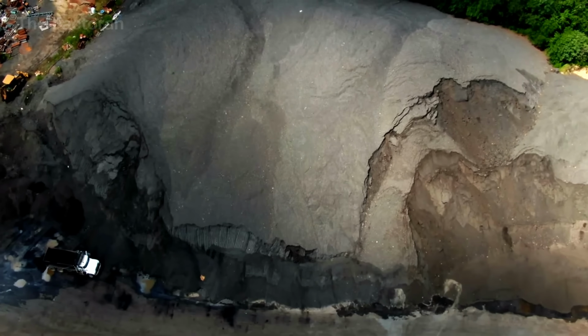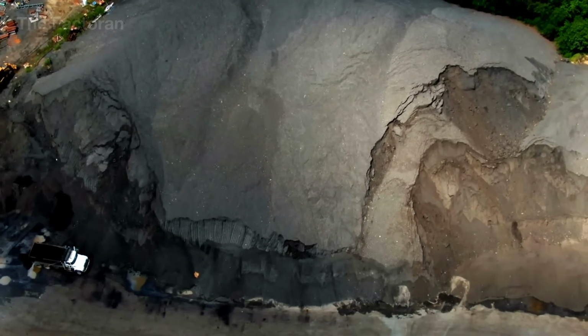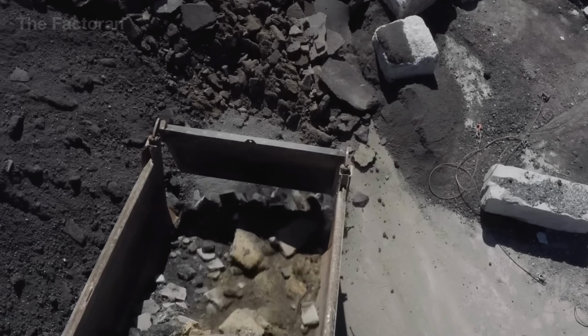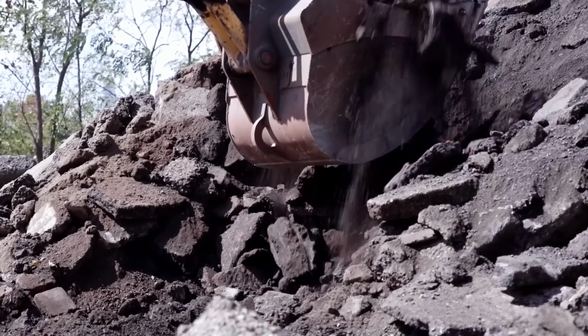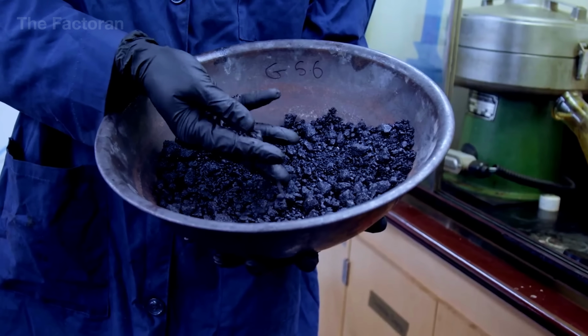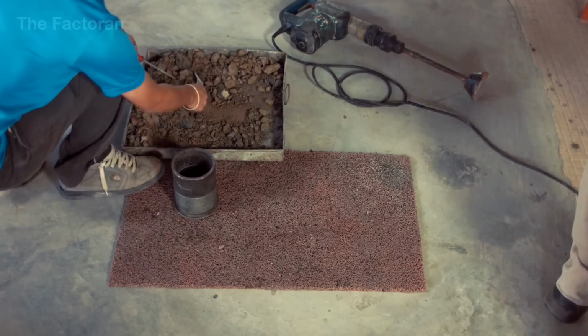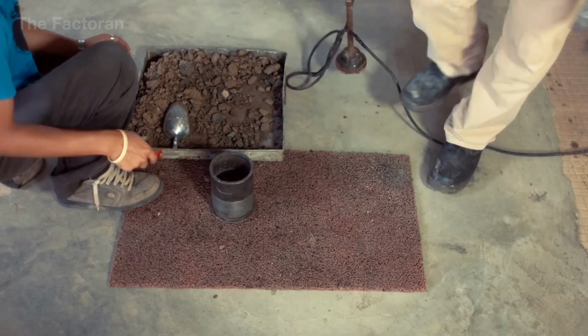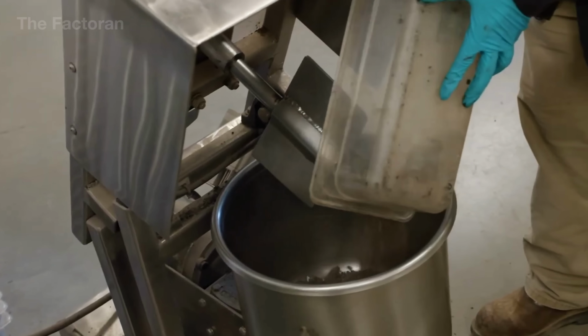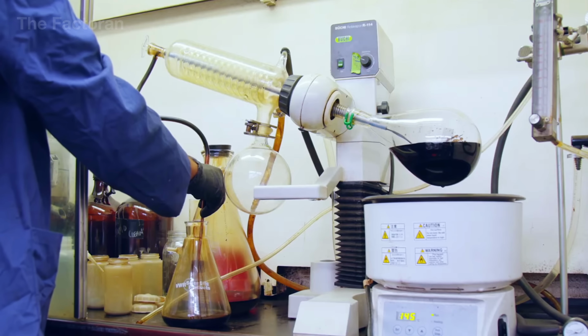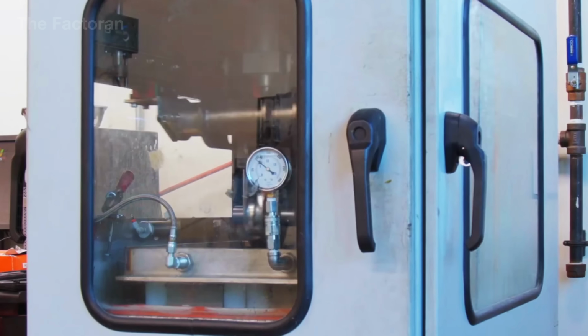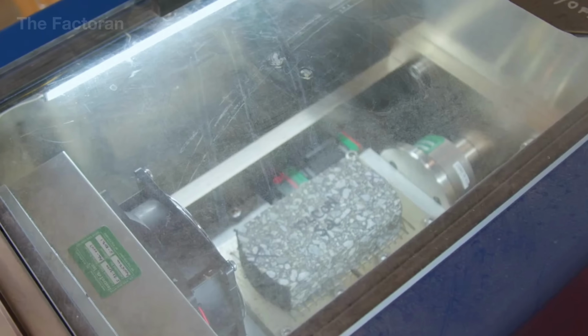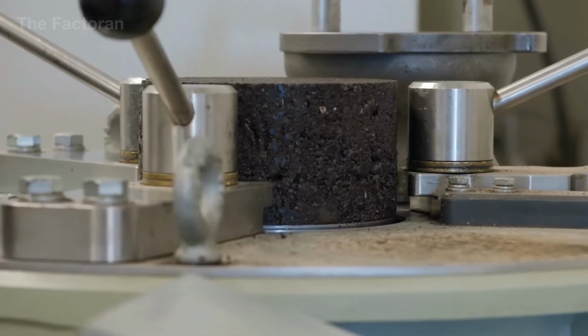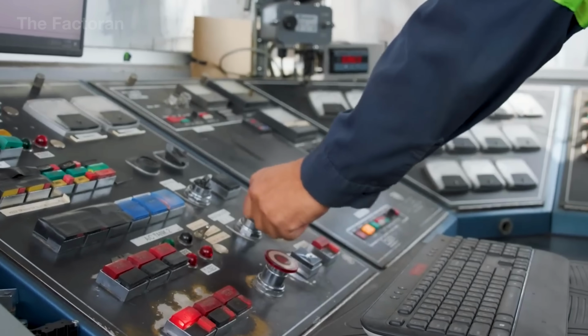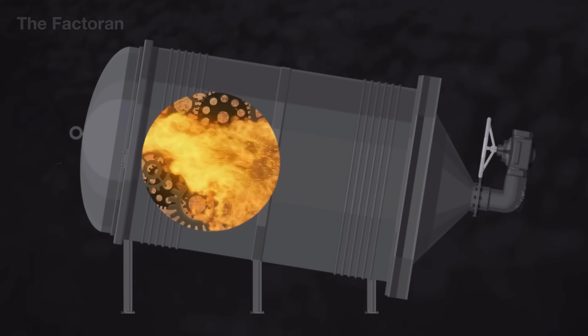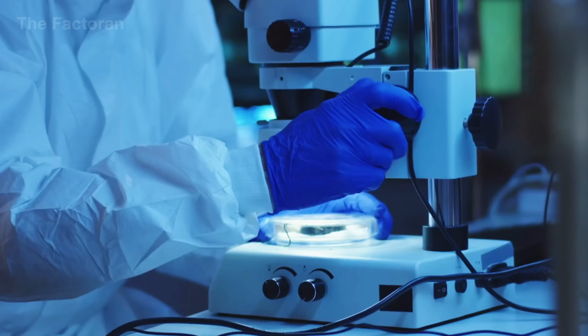First, the reclaimed material is fed into a rotary heating drum, where hot air removes moisture and softens the aged binder. Next, it passes through vibrating screens to be sorted by particle size. Part of it is fed directly into the mixer, along with fresh aggregates, while the rest can be stored as supplemental material. At the same time, new binder, virgin asphalt, is pumped in and blended with the RAP in carefully measured proportions by electronic scales. This restores the flexibility and strength lost in the old pavement, creating a uniform mix that meets technical standards.